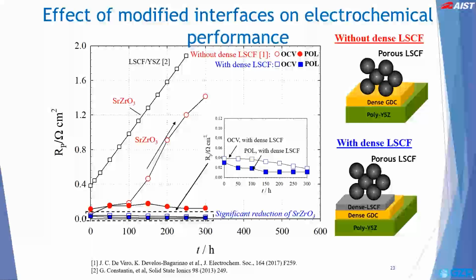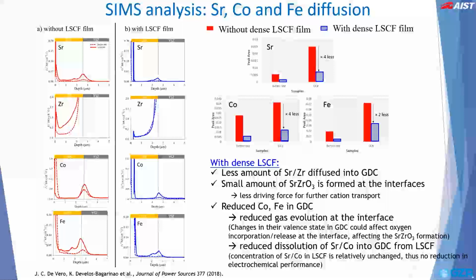We can see that the polarization resistance increases quite rapidly for the sample without dense LSCF, but shows relatively low and stable values up to 300 hours for the sample with dense LSCF. From these results, we can conclude that the degradation of the polarization resistance is greatly reduced by inserting a dense LSCF film, which improved the cell stability. Further analysis using SIMS was carried out to gain information about the diffusion of strontium, zirconium, including cobalt and iron across the GDC interlayer.